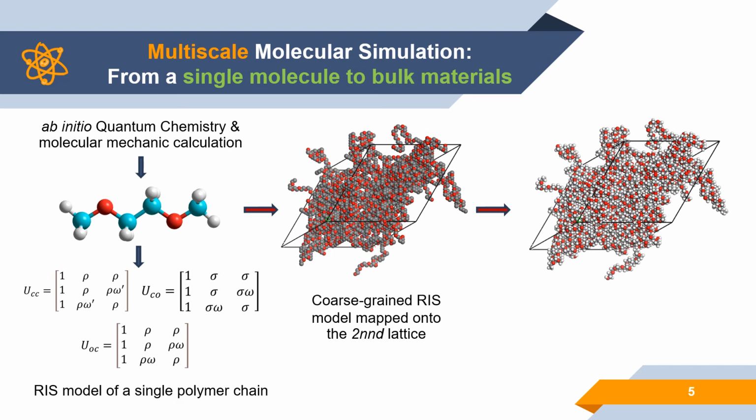Last, amorphous PO and PI are generated and equilibrated using multiscale algorithm in discrete space. After that, the fully atomic amorphous PO and PI model can be obtained by the reverse mapping procedure to recover the missing atoms followed by energy minimization.